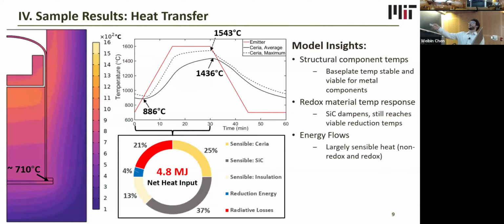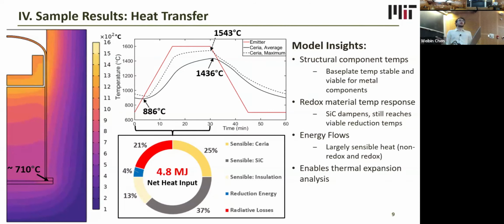And we can also analyze the energy flows in the first 30 minutes, which is the heat up and high temperature phases, to see where the energy is going. And we can see that about half of it is going into sensible heat of the structural and non-redox components. About a quarter of it is going into the sensible heat of the redox component. And the rest of it is either lost through the sides or is going into the reduction reaction. What our heat transfer model also enables is thermal expansion analysis, which I will get into next.